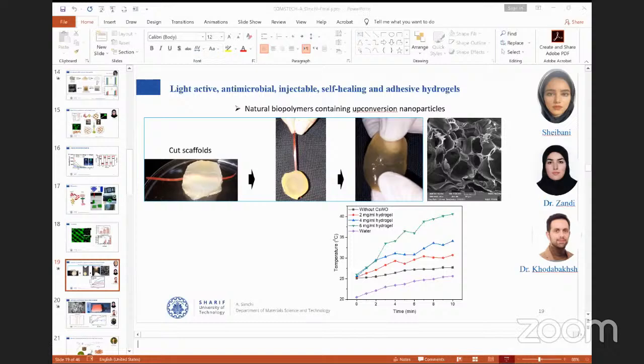In the following work, we had in mind to create and fabricate injectable self-healing adhesive hydrogels. So we went one step forward to make our hydrogel not only printable, but also light active. It means that irradiation of light creates antibacterial effects. And also the gels could be self-healing. So we use natural biopolymers containing upconversion nanoparticles, and we show that the gels can be cut in two pieces, as you see here on the left-hand side, cut a scaffold in two pieces and put it together, and again they integrate and make a three-dimensional scaffold without any problems.